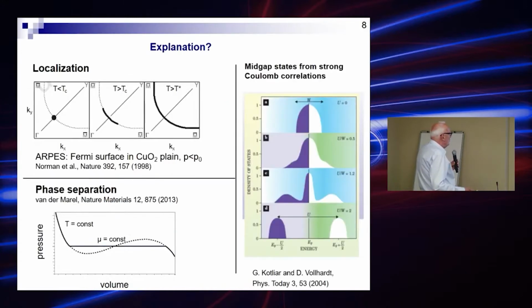What is the explanation of this strange constant chemical potential up to optimal doping? Only shortly, one possibility is localization. So you see this from this point in underdoped regime for T below TC, we have some arc for T above TC, and above T star we have the full Fermi surface. This is one possibility. The second possibility is van der Waals curve of coexistence of two phase.